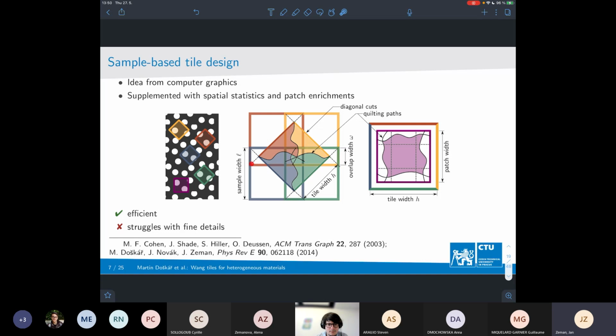In the second step, you cut each of these tiles diagonally, as you can see here. And when designing one tile, like the one shown here, you take one of these halves and allocate it to a given tile. This is then the edge of the tile, and because you are cutting it in half here, you ensure that everything will be continuous as you require. Because of that overlap, however, you have certain regions in the resulting structure where there is some ambiguity in which patch of the microstructure needs to be used. So you must invoke an image quilting algorithm in order to take these pictures and literally sew them together. So this is what we did.